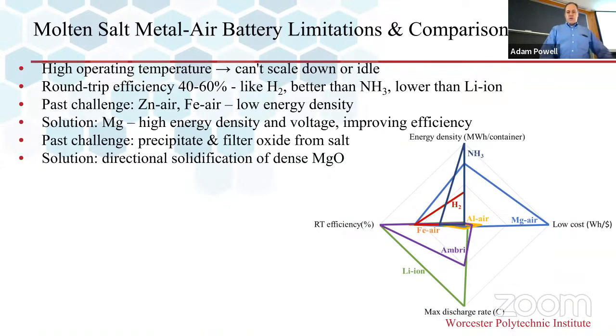If we look at the figures of merit, the round trip efficiency is considerably lower than lithium ion, comparable to iron air of Form Energy, but much better than ammonia, with not quite the energy density versus a tank full of a container for the ammonia tank. But ammonia is, of course, toxic and explosive, et cetera. Hydrogen as well, so much better energy density than hydrogen, better than ammonia, and very low cost as well.